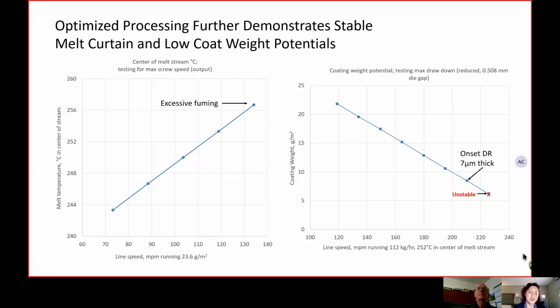Thanks, Andy. Yeah, so the first part of our experimental design was finding what speed we can run the PLA where it's not degrading and get the most rate, but still have quality resin. So we increased the line speed and the extruder output in ratio. We're maintaining a constant coat weight and increasing the speed, so the screw's going faster and the line's going faster. And the melt temperature is going to increase with the extruder output. You can see eventually we get to a point where above 252 up to 256 melt temperature in the center of the stream, that's really too hot for PLA and you're going to have degradation. And we observe outside, coming down the melt curtain, excessive fuming, very significant fuming.